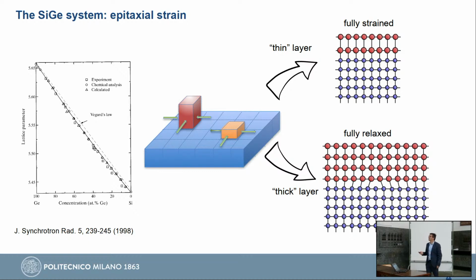As far as the lattice parameter is concerned, germanium has a larger lattice parameter, so this is the variation of lattice parameter of silicon and germanium as a function of composition. Again, we have a continuous behavior, but essentially the lattice parameter of germanium is approximately 4% larger than the one in silicon. So if I try to put, for example, germanium directly on silicon, I can have two main cases which are interesting for research and for application.